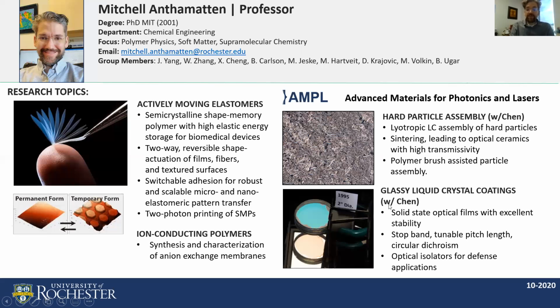And in another topic, we work with a class of materials called glassy liquid crystals. Glassy liquid crystals are soft materials that form a liquid crystalline state at a high temperature, but when they're cooled, the liquid crystalline state is preserved and they form a glassy state where they're kinetically trapped. And so we can take the advantage of the ordering of a liquid crystal and combine that with solid state optical properties.